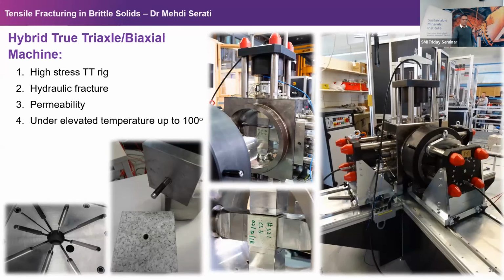No, that's absolutely true. Just 2 days ago, we submitted a $2.2 million LIEF project, a linkage infrastructure grant, whatever the acronym is, with my colleague. I'm not the lead here, I'm just fortunate to be part of the team. It's a 4D dynamic CT scan, with around 1 million requested from ARC and another contribution from the UK and a contributing university. That's exactly what would enable this type of research, where you put the sample inside the load frame, but it's very fast. The beauty is that it's different from other available CT scans, for instance at UNSW, in that you can do near real time relative to what is available in the market.